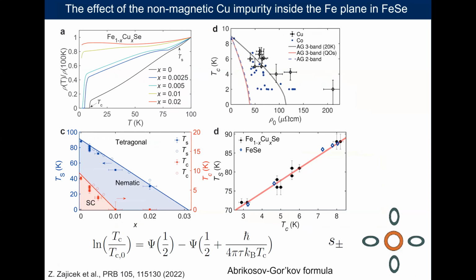Now, what happens if we add an impurity to the system? Interestingly, if we add a copper impurity in this conductive layer, then the material becomes very non-metallic. And one can look at the variation of Tc versus the residual resistivity and establish that this follows the Abrikosov-Gorkov formula for an S plus minus system.